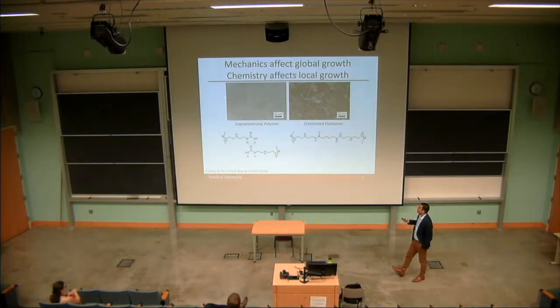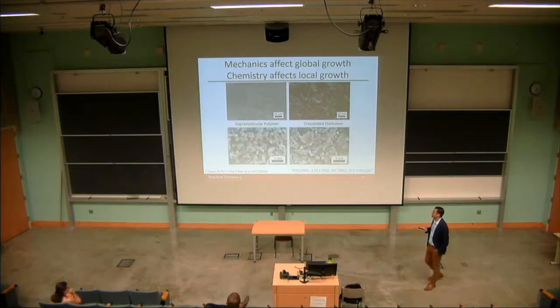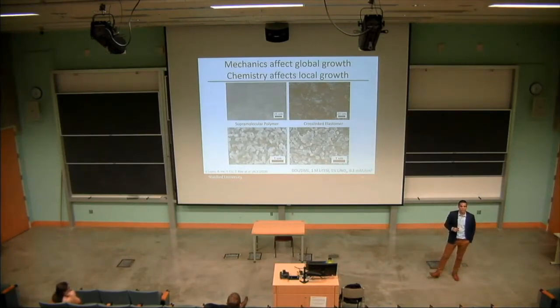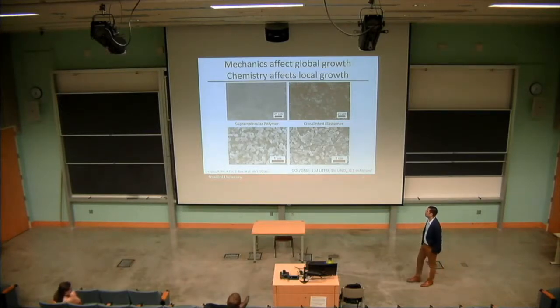And you can see very easily, this is SEM of a large portion of the electrode. Here, it's highly uniform, those small nuclei. But with the elastomer, we see, again, this patchy, poor quality deposition. And so we see that very quickly, the mechanics are really important for the global growth. But when you zoom in on these SEMs and you look at the small particles individually, you see that these look very similar. And so what that tells us is while the mechanics are really important for the global properties of these electrodes, the chemistry is really what's driving the local morphology of the lithium.